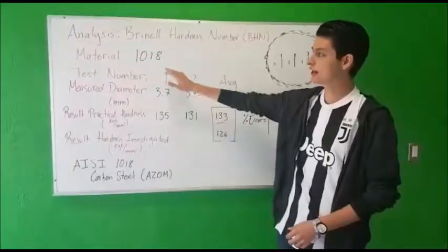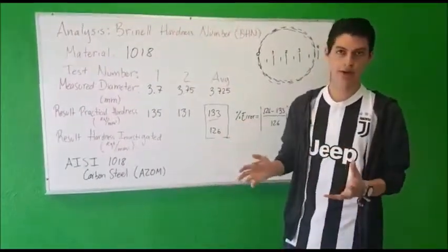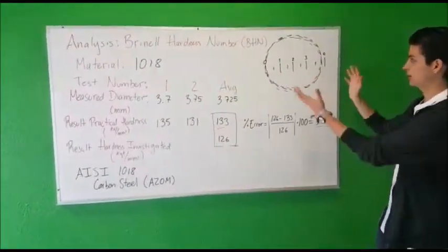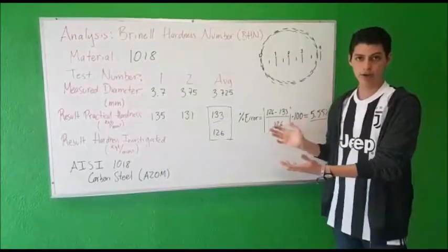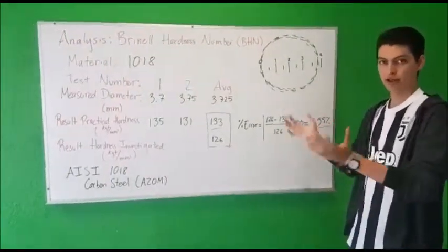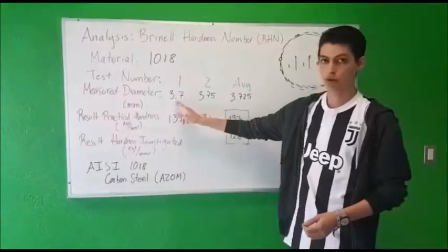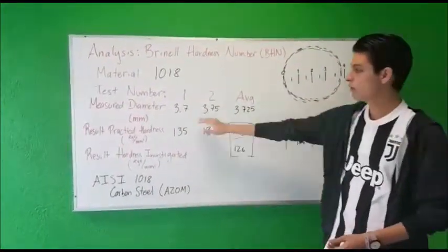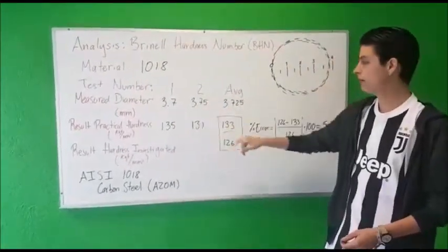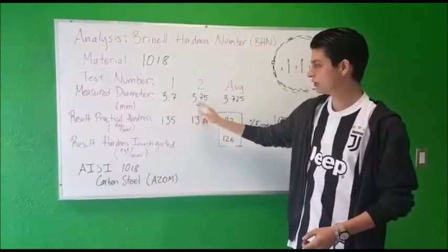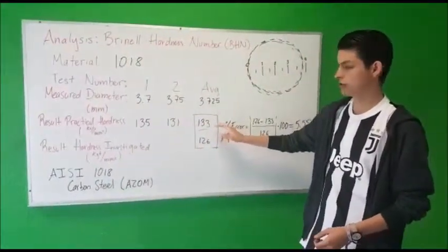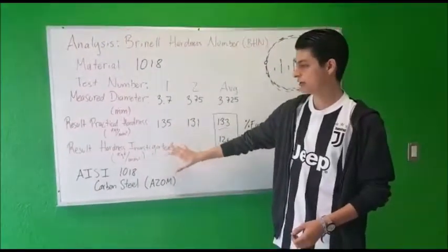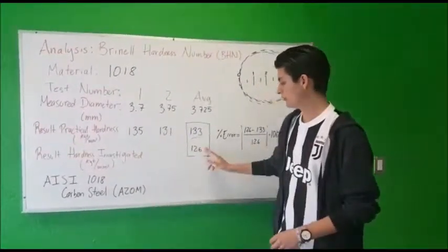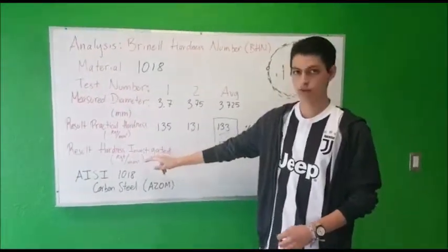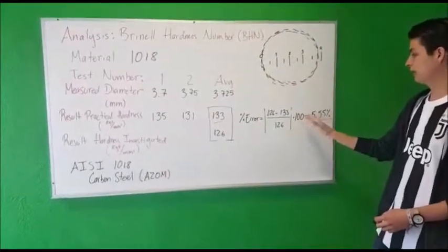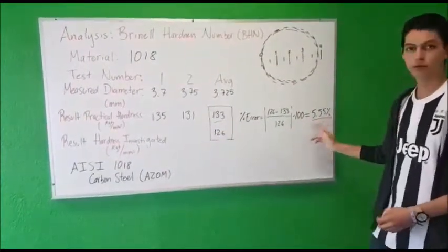The next test we performed was on the 1018 steel, which is in theory softer than the 1045, and we can see that in the diameter. It has a much bigger diameter than the last one, because the force causes a bigger indentation. The first diameters we could make out were 3.7 and 3.75, which gave us this average. Then we searched each one in the tables and got an average of 133. Then we investigated the real result, which was 126 kilogram force over square millimeter, and we got a percentage of error of 5.55%.